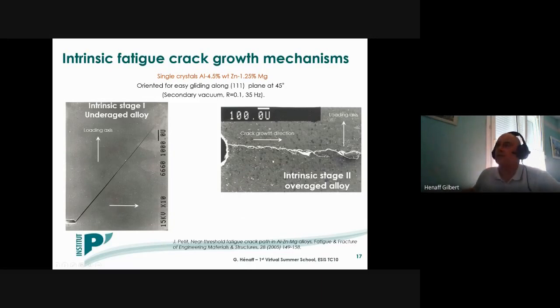The most classical, which is observed here in the case of a single crystal of aluminum zinc magnesium alloy, oriented for easy gliding, but with two different heat treatments, one overaged, one underaged. In the case of the overaged alloy, here you have the notch, the crack emanating from the notch. This is the loading direction, the crack growth direction. You can see that we have a crack path, which is quite straight and perpendicular to the loading axis.